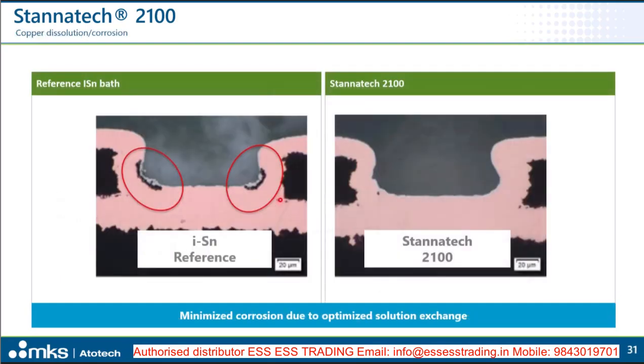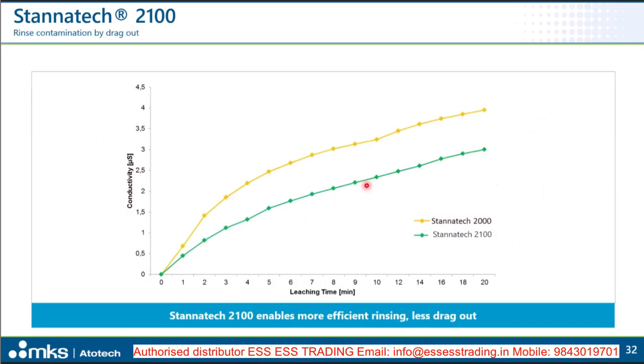And this reduction of the viscosity helps in two ways. In one way, it improves the exchange of the immersion tin solution during the plating in narrow areas to prevent, as mentioned in the beginning, excessive corrosion in really narrow regions in blind microvias or any undercuts, to have a better exchange, providing fresh tin solution, and to not have this mismatch of excessive copper dissolution in areas where no tin can be provided. Another benefit is a better rinsability. So it's easier to get rid of the chemistry.